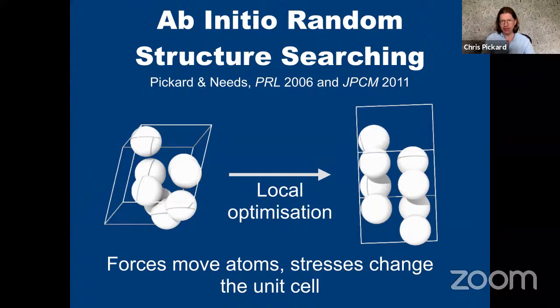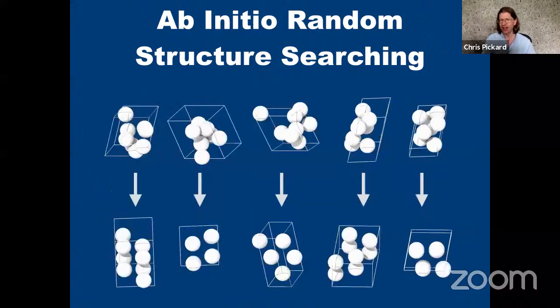But if you do it many times, and this became possible because at the time I was developing this method, multi-core computers were coming available. And so parallel computation was democratized. Everyone could have a parallel computer. And so the idea of doing many calculations at once was just obvious. This sort of high throughput approach also found a home in, for example, Gerd Ceder's Materials Project, which was similar in spirit in that it made use of these newly very parallel computers, except the source of their structures for the Materials Project database were the existing crystallographic databases, the ICSD or other databases.